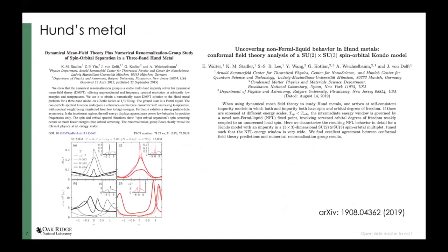From it, they tell us that for the Mott case you should have a significantly reduced density of states when you enter the Mott physics, while for Hund's metal physics you still have a lot of density of states, meaning you never fully gap the density of states at the Fermi level. This is stimulating in a sense. It can help us understand the Mott metal phase and the coherent-incoherent crossover.